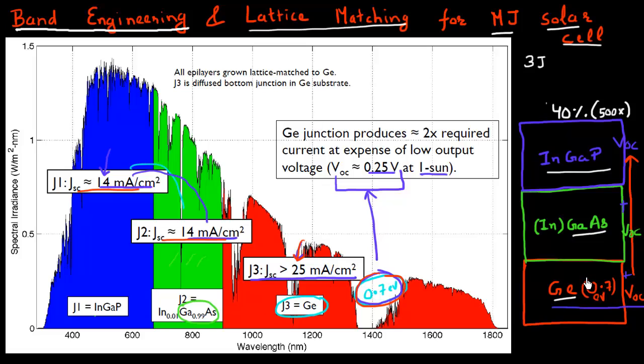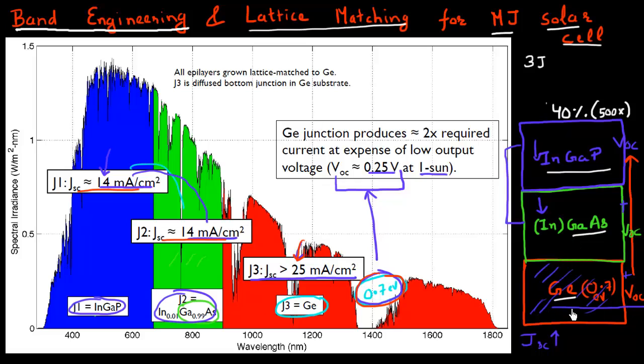So what do I do about it? There are two ways I can get around this problem. One is to lower the band gap of the top cell and the intermediate cell, so they will absorb more of the spectrum. The short circuit current of these two cells will hopefully increase and become closer to what germanium gives, improving the overall short circuit current and efficiency. The other way is to replace this germanium with something else which has a higher band gap, so the short circuit current of the bottom cell will decrease but its open circuit voltage will increase, hopefully giving some increase in efficiency.